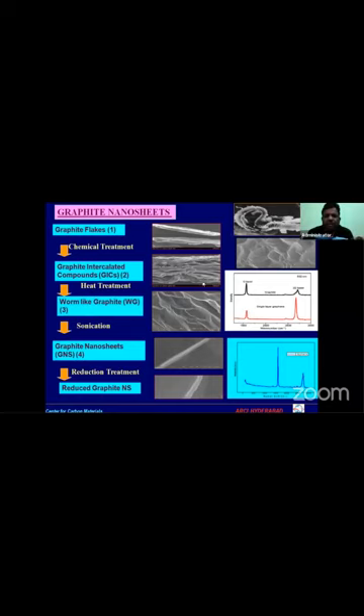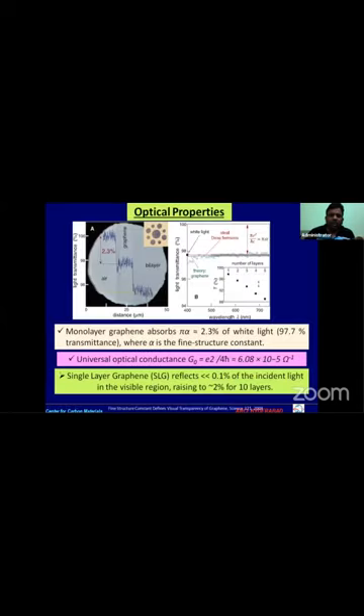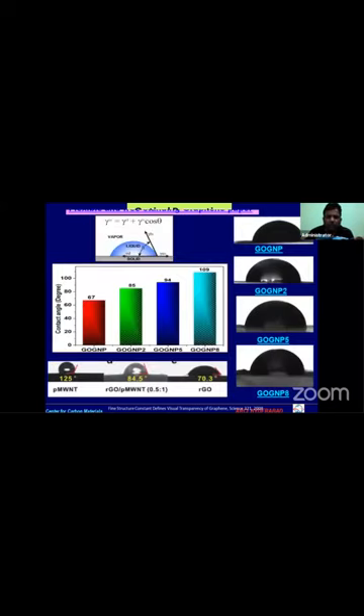This is graphite. Again, it has to be characterized by Raman and other techniques to assess the quality of graphene. You can see the carbon material, which is black, but it can transmit almost 97.7 percent of light. So that's the beauty of this material, which is unique by its own. One can make this graphene from hydrophobic to hydrophilic by different treatments. Our group is also exploring many applications based on that.